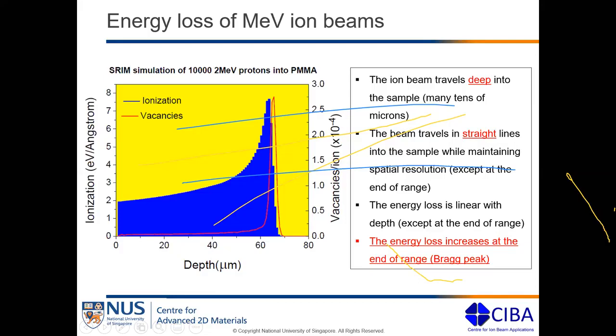The energy loss of the protons is more or less linear as a function of depth, but it jumps at the end of the range, right? So this jump or this kind of sharp peak at the end of the range of the ion is called Bragg peak, and this happens particularly for this kind of high energetic ions. Now, this Bragg peak can be useful for many applications, and I will talk about that later.